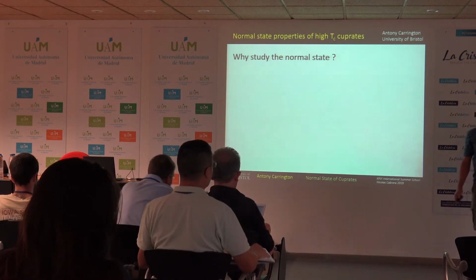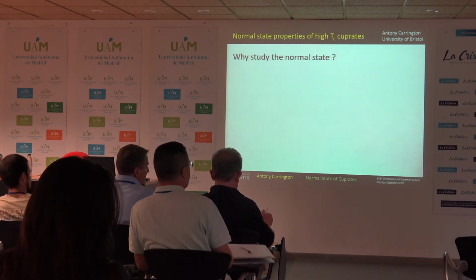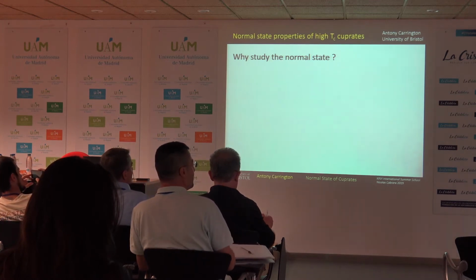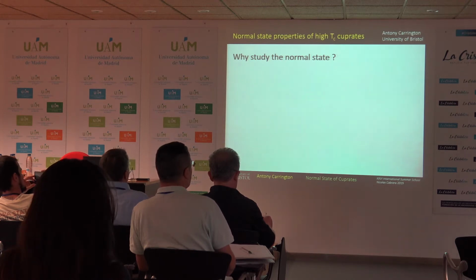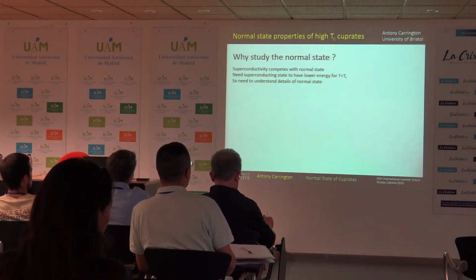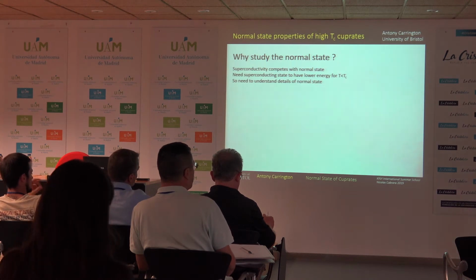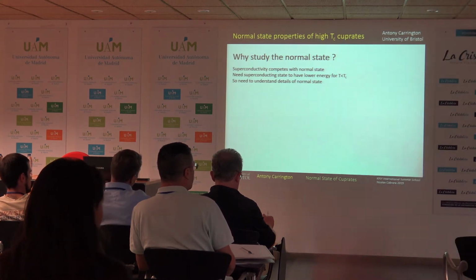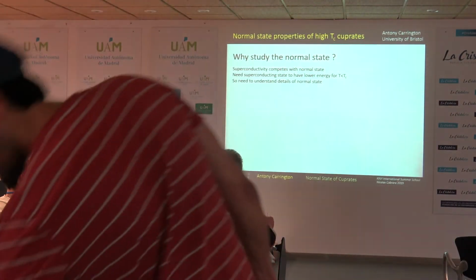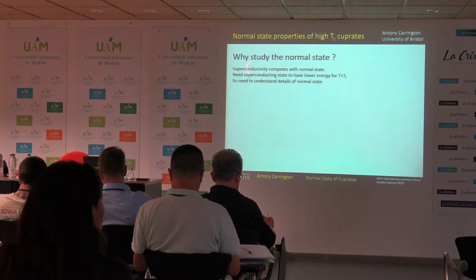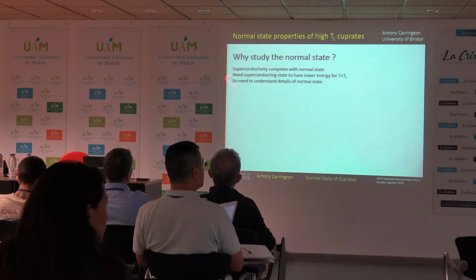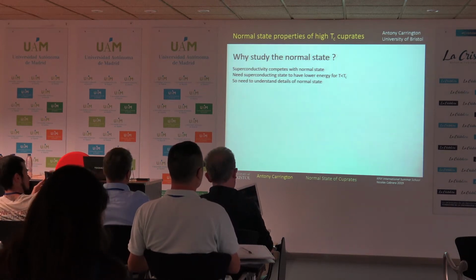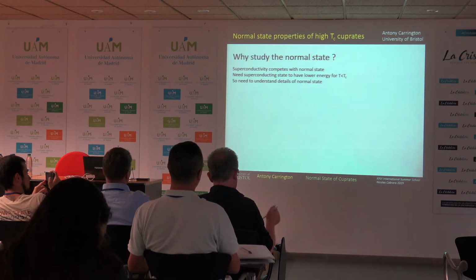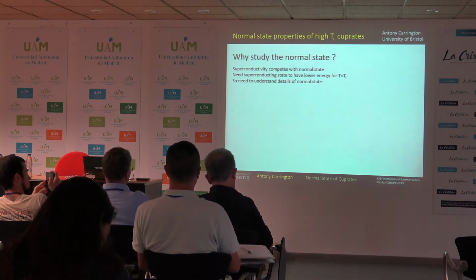superconductivity approaching room temperature. And so the first thing you might ask as a student is, why don't you study the normal state anyway, right? It's not superconducting. Well, the main thing is that on a very simple level, the superconducting state is competing with the normal state. It's got a lower energy than the normal state, and that's where it superconducts. So obviously, if you want to understand why the superconducting state is the preferred state, you need to understand what the normal state is in the first place. So what is the superconducting state competing with? Okay, so that's the sort of perhaps most fundamental reason.